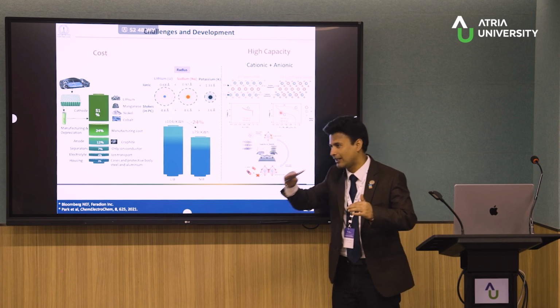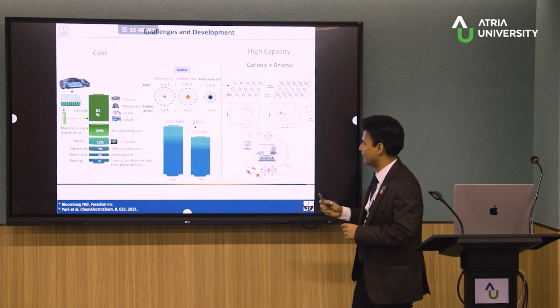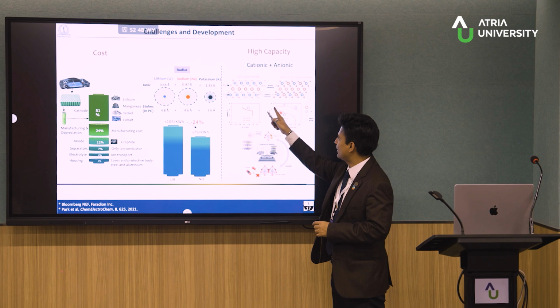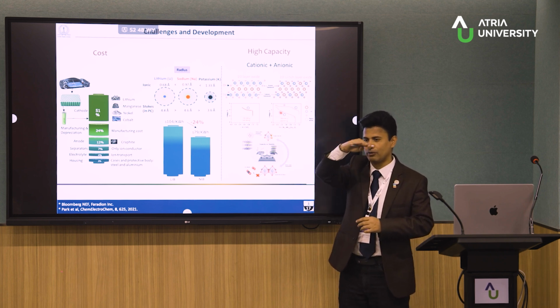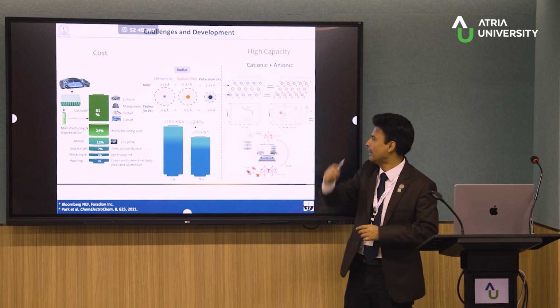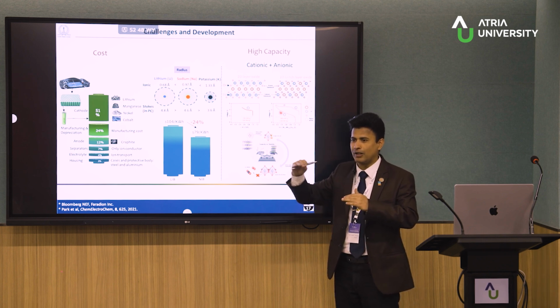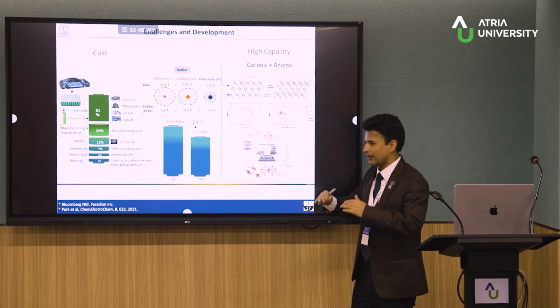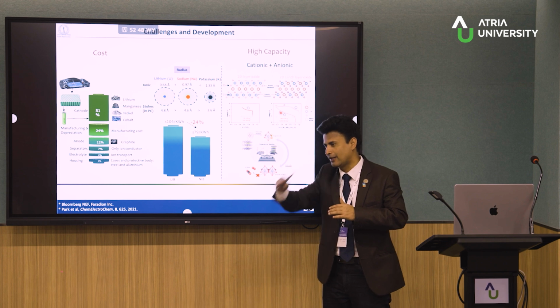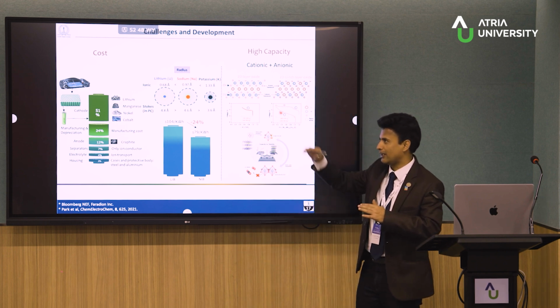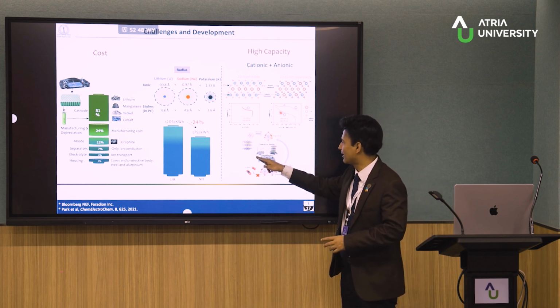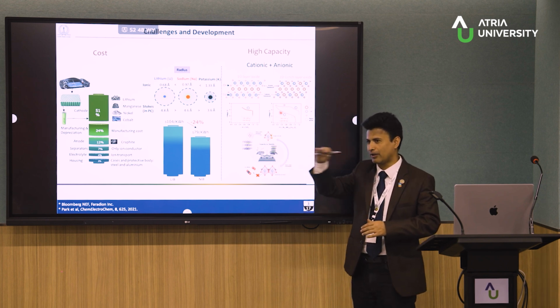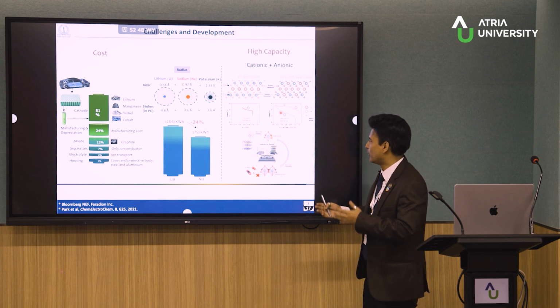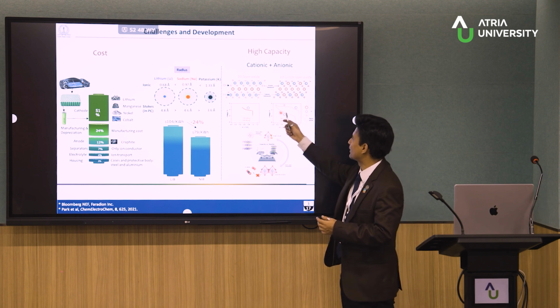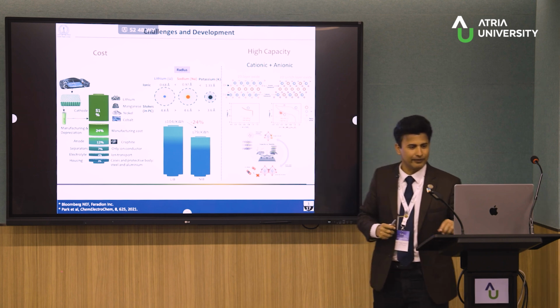After some time there is a degradation of the capacity. There's a big problem. If you change the voltage, if you cut off at 4, 4.1, 4.2, 4.3 volts, accordingly you will trigger different amounts of anionic redox. Accordingly the capacity will go up, but the cycling stability will go down. So there is a balance between capacity and stability. So what will be the real cut-off voltage by BMS, where we can get a little better than cationic plus anionic capacity? Anyway, these are different concepts.